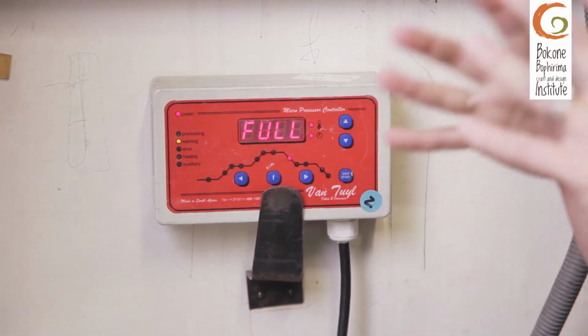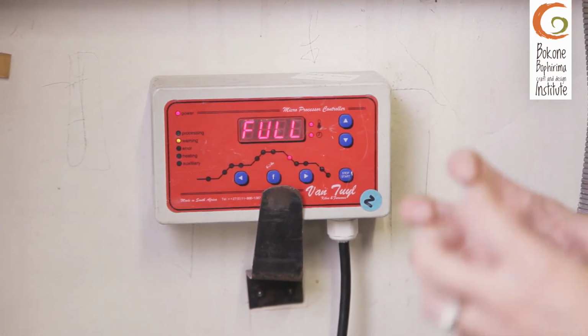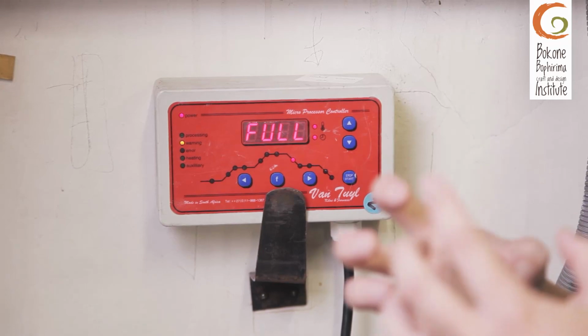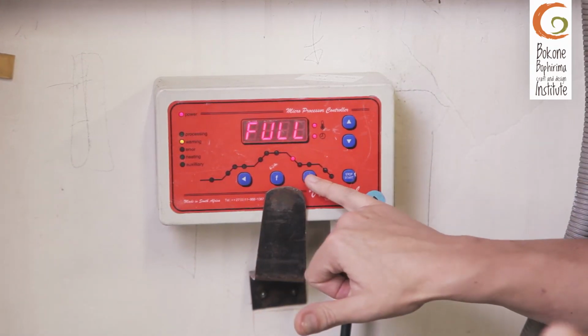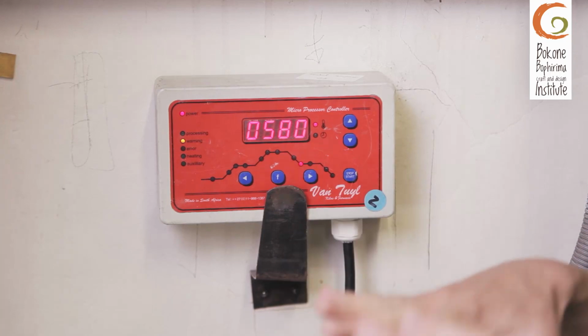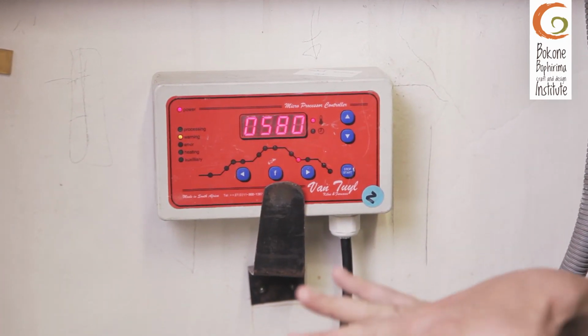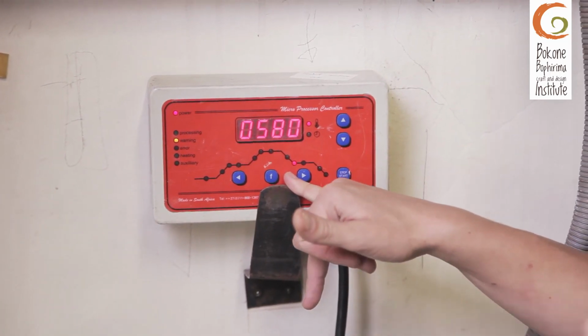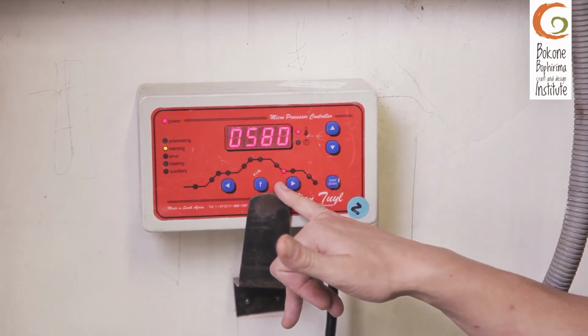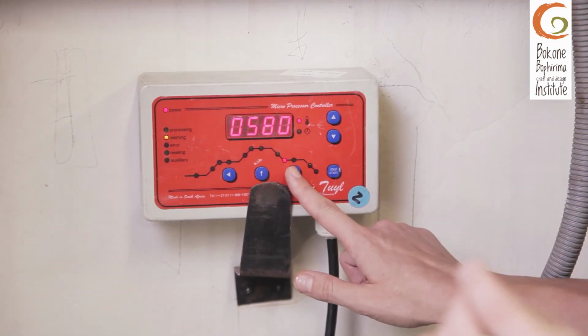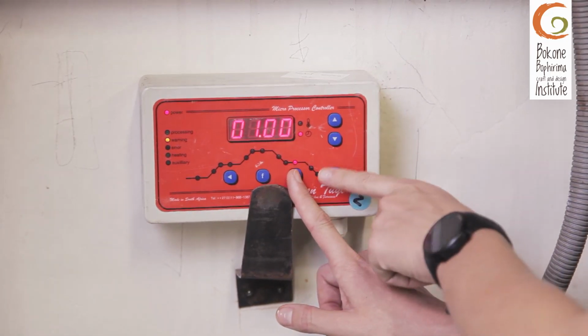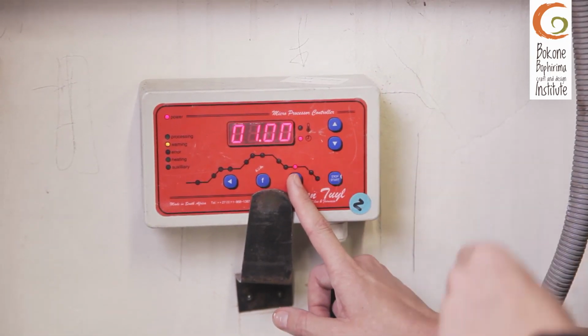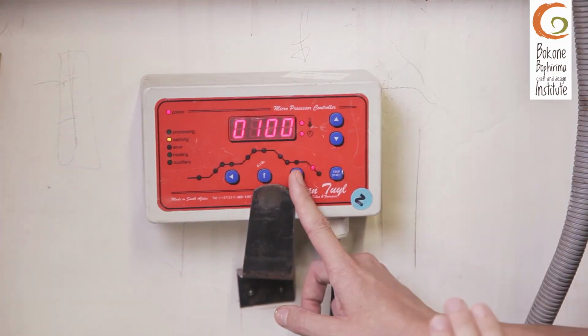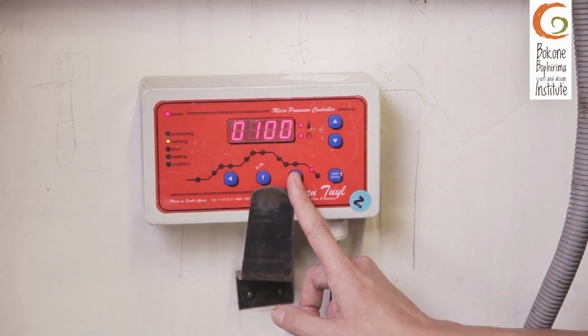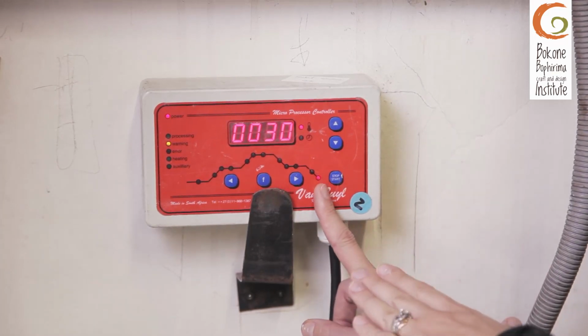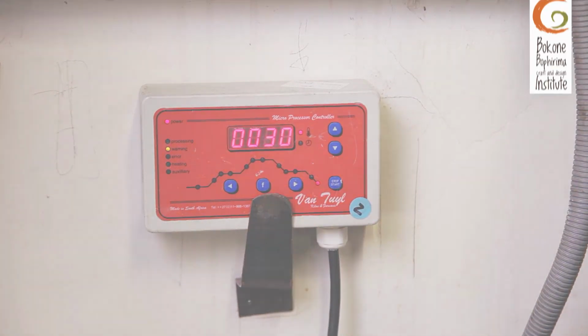This going down is our crash cooling, so this will be able to help us to freeze our glass in that process that we have just seen in the kiln. And then we'll go down to a temperature we normally want to hold our glass, and then from this process we talk about annealing. So we want our glass to go down slowly, therefore that it doesn't crack. Again, we can have a delay of temperature, and then we could go down with our annealing slowly as possible, depending obviously on the thickness of the glass, until normally room temperature or 30 degrees, where we are able to open up the kiln.